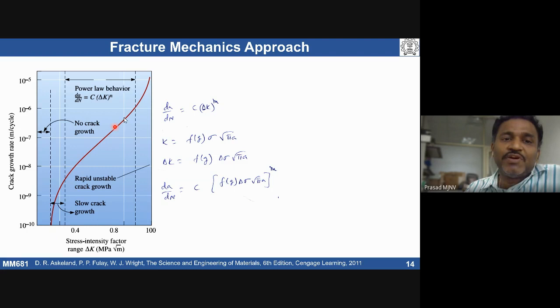So this power law behavior is basically that dA by dN, the crack growth rate, is equal to C delta K to the power of sometimes N, sometimes M. Most of the textbooks use M. So dA by dN is equal to C delta K to the power of M. This equation was proposed by a scientist called Paris. That's why it's called Paris law. This is the equation derived for the power law behavior.